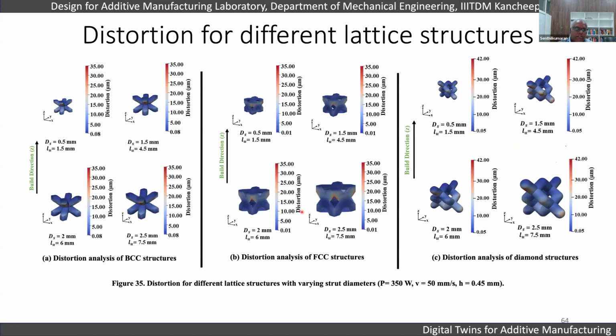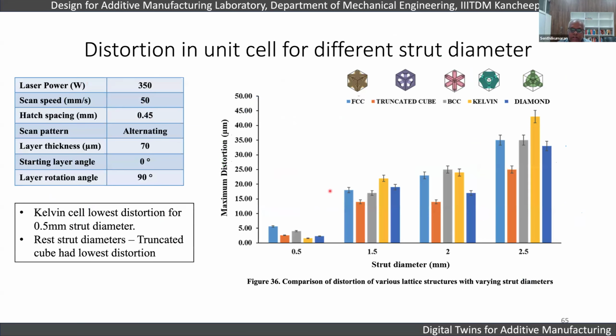So we tried to simulate the distortions for different lattice structures, just starting with the unit cells alone, and then we built at the part level. So we had some results based on it. For example, this is the size effect.